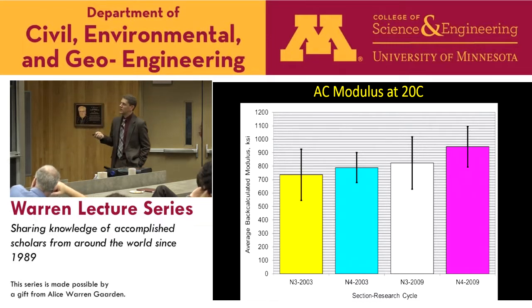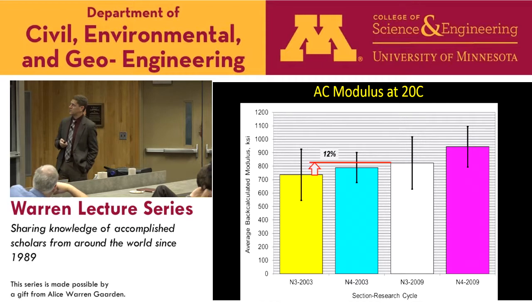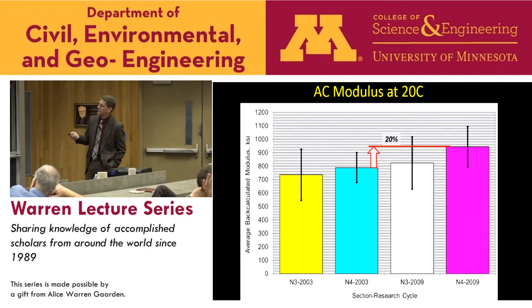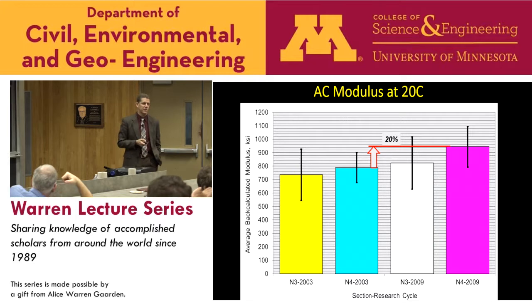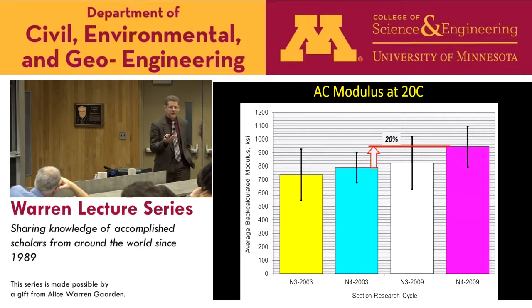So what these are showing is, from 2 different test cycles, 2003 and then 2009, the modulus of the materials in place. Between 03 and 09, we had a 12% bump in that modulus, it got better with time in terms of stiffness, and on this section, those 6 years increased it by 20%. So that's a clear indication that there's no damage accumulating, and actually the modulus is increasing over time. In turn, the strain at the bottom is decreasing. It's getting better as we go along, and that's a good thing.